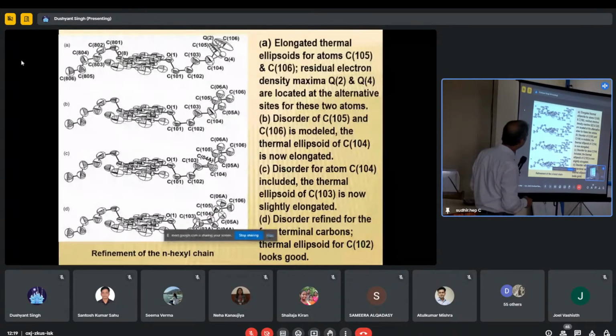I have bifurcated into 2 parts. Now the disorder has gone from C104. Now you can see C103 is not that much elongated, but still it is showing some kind of small disorder. Maybe it is 50%, it may be 30%, no, it may be 20%. We have to resolve this also. We have resolved this. Now you can see C102, it is almost showing nil disorder. Even disorder of 5% we can ignore.